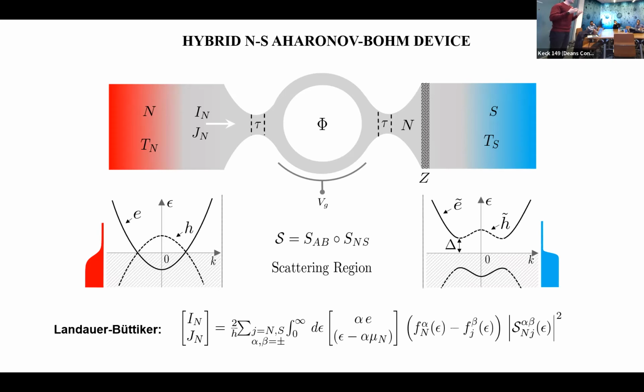So the way we want to characterize the thermodynamical properties of the system is by using the so-called Landauer-Büttiker formalism, that indeed allows us to compute the charge I_N and heat J_N currents, for example, flowing to the normal lead. Without entering too much into the details of the formula, I just remind you that here the square modulus of the scattering matrix corresponds to the transmission probability for electrons and holes to go from one lead to another. The difference of the Fermi functions gives us information about the occupation of electrons and holes in the leads. And also here I used e, which is the charge of the electron, to compute the charge current, and the difference between the energy and the chemical potential to compute the heat. I stress here that alpha and beta are just labels for particles and holes. So this is the Landauer-Büttiker formalism generalized to the case of superconductors, in which you have indeed particles together with holes.